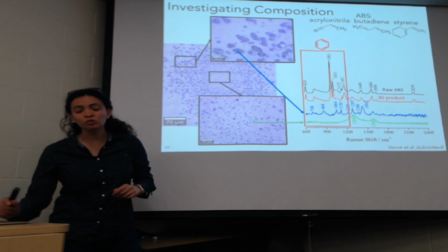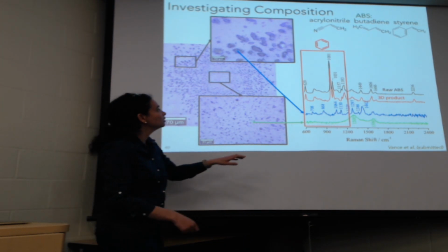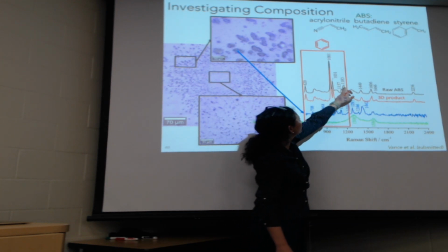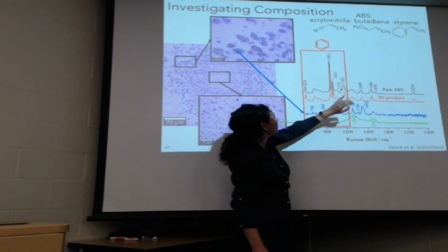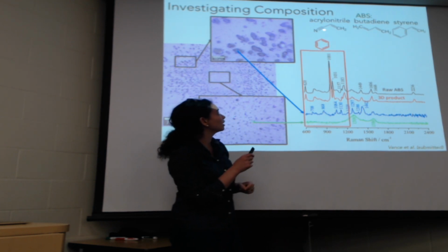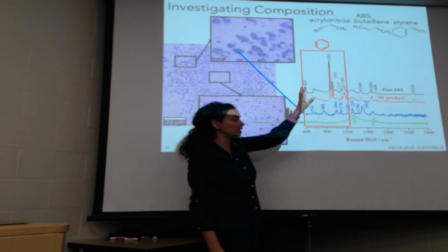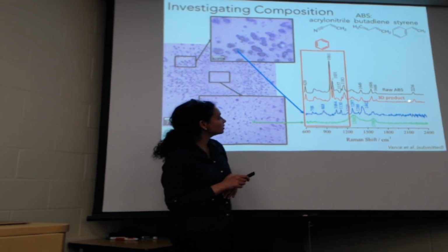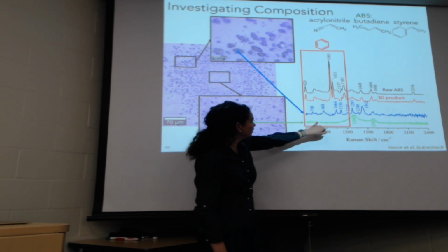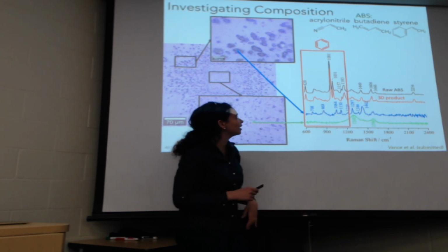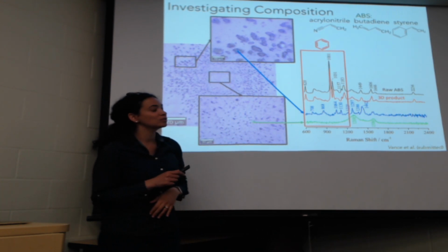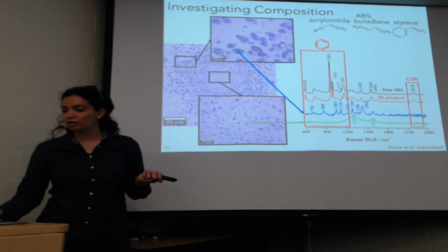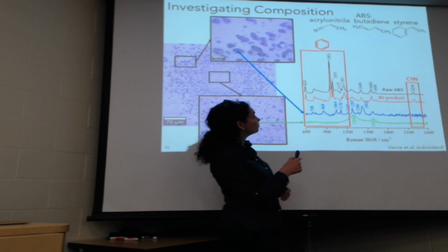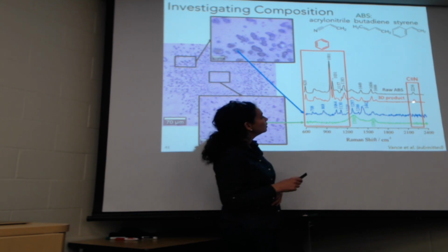So there are two peaks that are very important here. These three peaks here, one, two, three, actually five, but the three major ones, are characteristic peaks for the benzene ring. So we can tell that if a sample has those three, it has the benzene ring. The raw ABS had it, the 3D part had it, but we couldn't really find it in the aerosol, in the particulate matter. They weren't really there. So that showed us that the styrene was not present in the aerosol from ABS. And then there's another important peak, the triple bonded carbon with the nitrogen that I mentioned before. We know that peak is representative of it, and here it is in the raw ABS and in the 3D product, but it's not there in the aerosol.